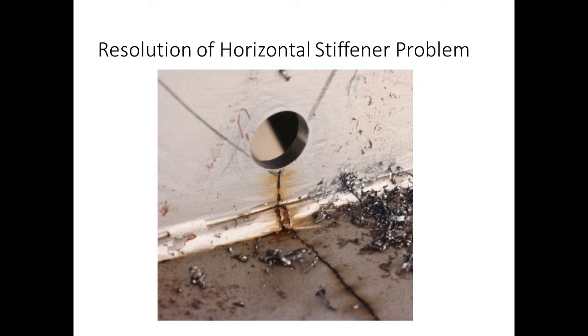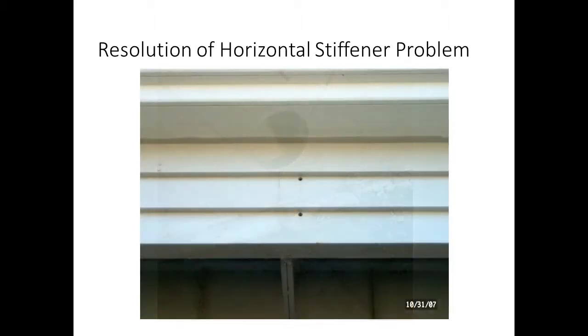Now, the inspectors knew that they could find these cases, but they were concerned about the welds that were out there where a crack hadn't nucleated yet. And they had a problem finding these butt welds in the stiffeners because the fab shop ground the reinforcement flush. So to deal with this, they shot down the stiffener with ultrasonic shear wave testing, and they were able to readily identify the incomplete penetration welds. And when they did, they preemptively put check holes above and below those locations so any cracks that developed wouldn't jump into the web.